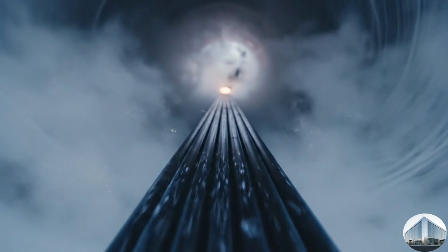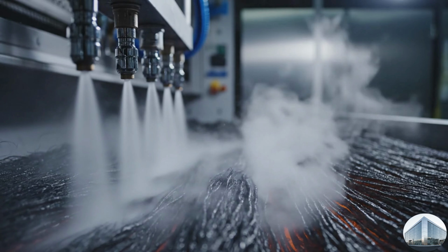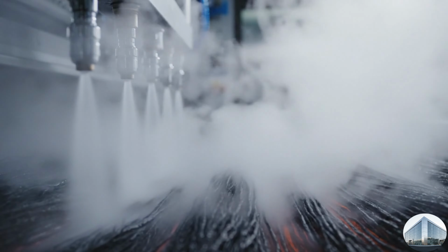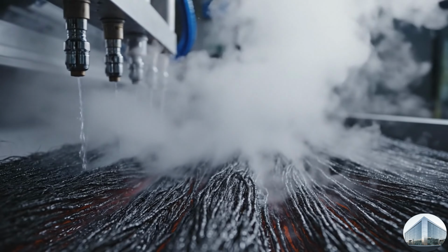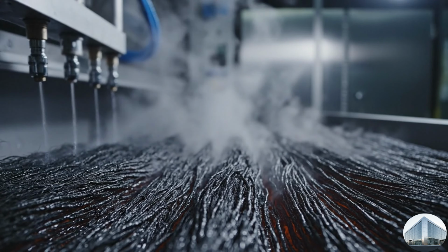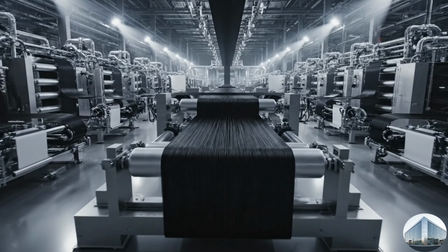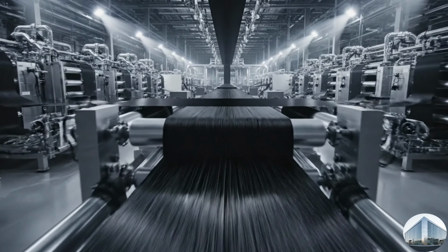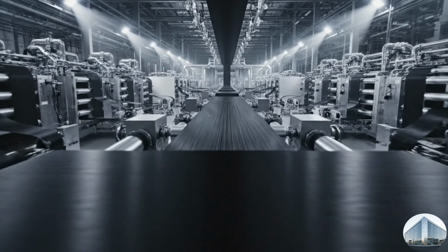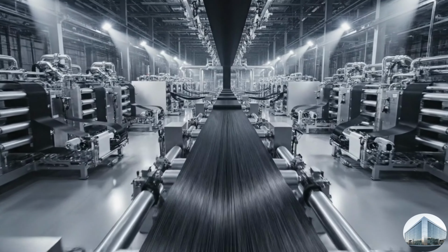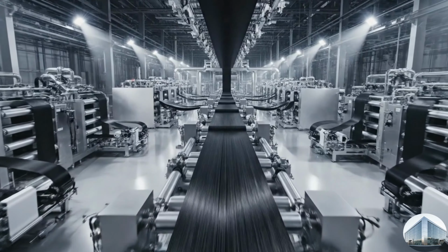What emerges is true carbon fiber. It is now jet black, sleek, and incredibly strong. It passes through a cooling zone to stabilize its new, hardened atomic structure. Rapid but controlled cooling is essential. The transition from intense heat to room temperature must be handled carefully to prevent any internal stresses from weakening the carbon strands. The transformation is complete.